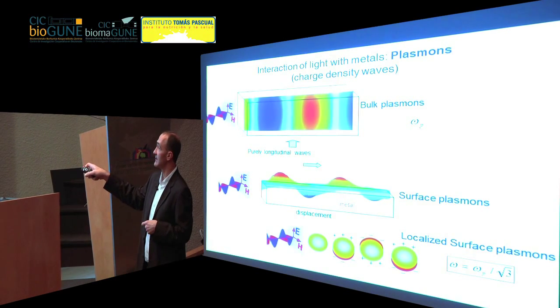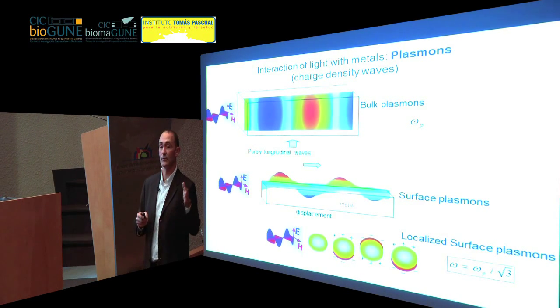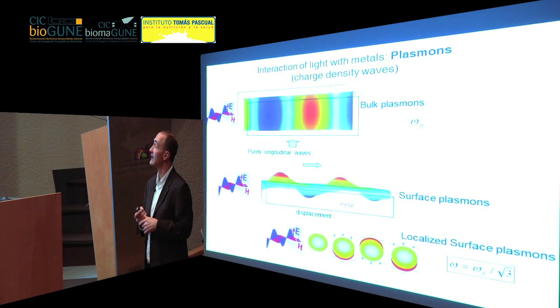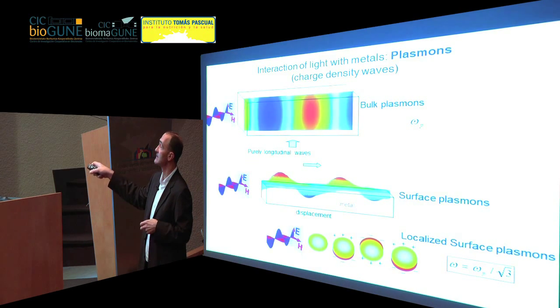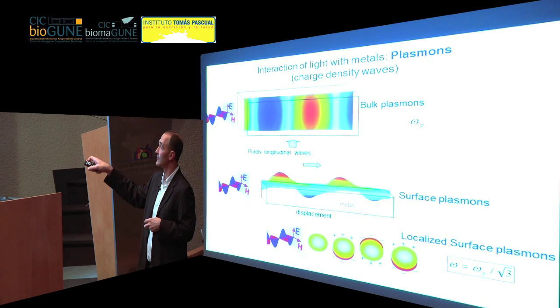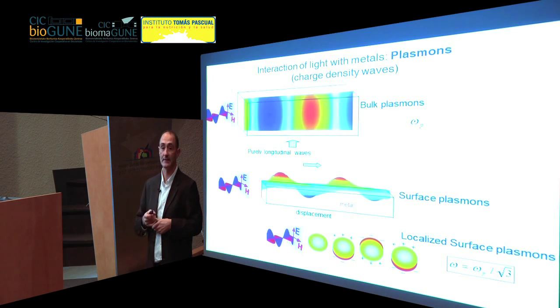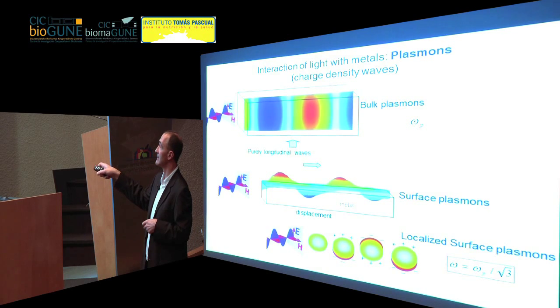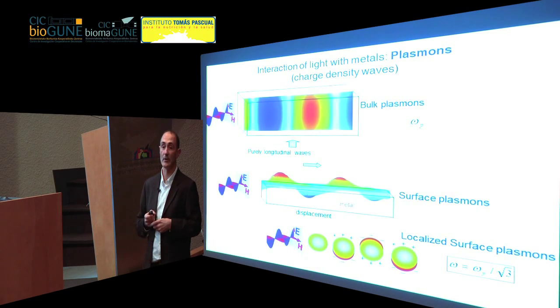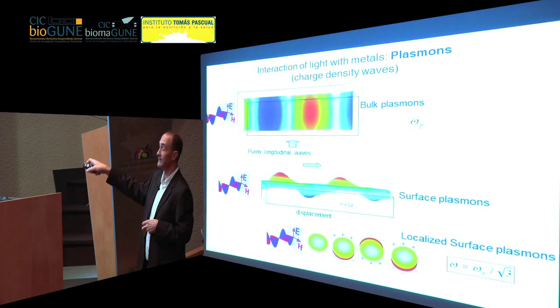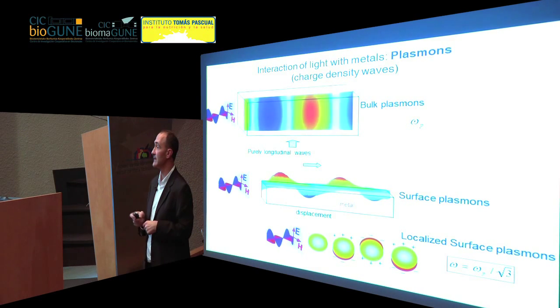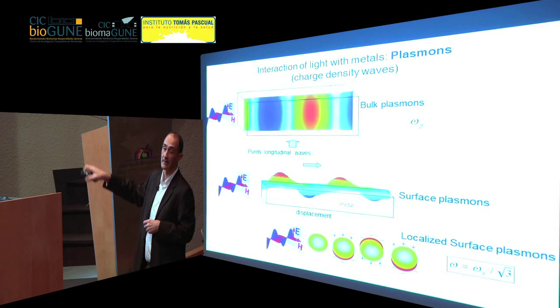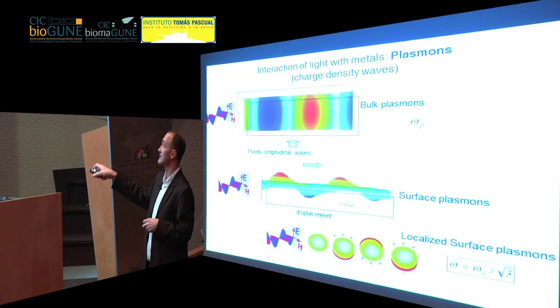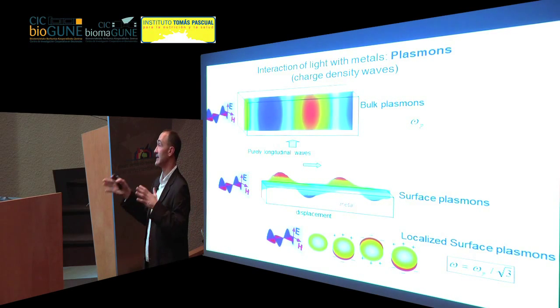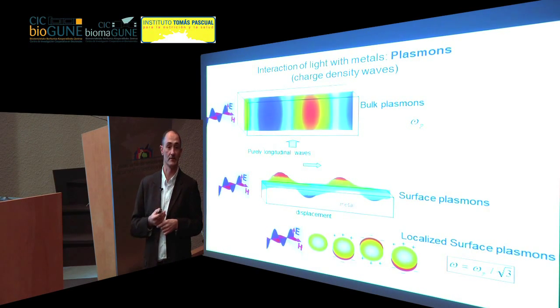So this is something that we have in metals. You can come with an electromagnetic wave of a specific frequency, and you can excite the formation of charge density waves in the metal. And this is specific for each metal, and each metal has a specific plasma wavelength. If you have a very thin film of a thickness of a few nanometers, then these waves cannot travel inside of the metal, so they are confined at the interface. And then we have the so-called surface plasmons, and the resonance condition is called surface plasmon resonance.